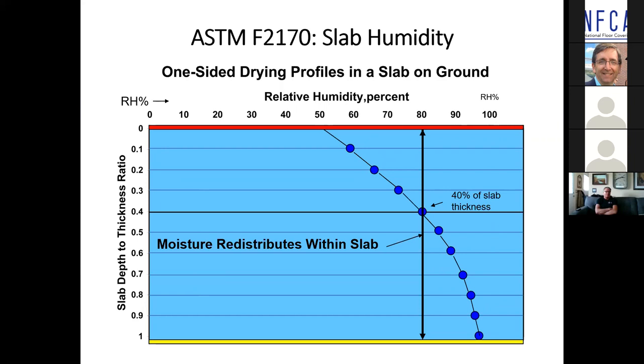Where the calcium chloride test is testing basically the driest portion of the slab. I mean, the slab is placed. Okay, you cover cured it, you took the cover off. It's drying from the top down. The surface region of the slab is going to be the driest portion of the slab. Here, we're actually able to predict what's going to happen to that dry portion after you cover the slab.